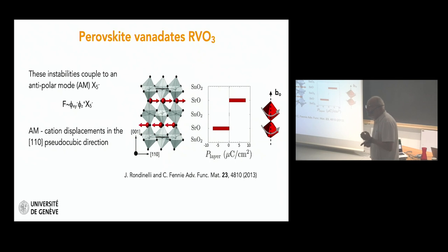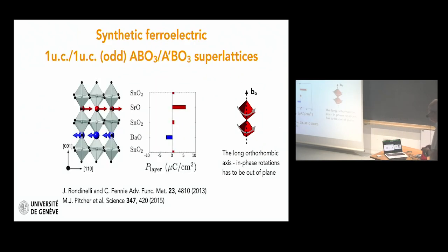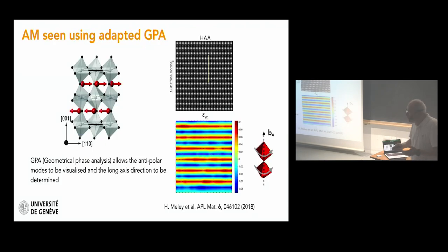But this has been studied because there has been a proposition by James Rondinelli and Craig Fennie that one could use eventually this antipolar motion to realize artificial ferroelectric material. And the idea is shown here. If you grow superlattices with two perovskites, ABO3, A prime BO3, and you realize odd superlattices, for instance, one unit cell, one unit cell,